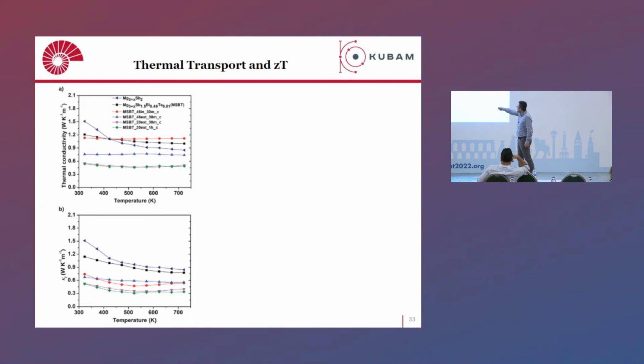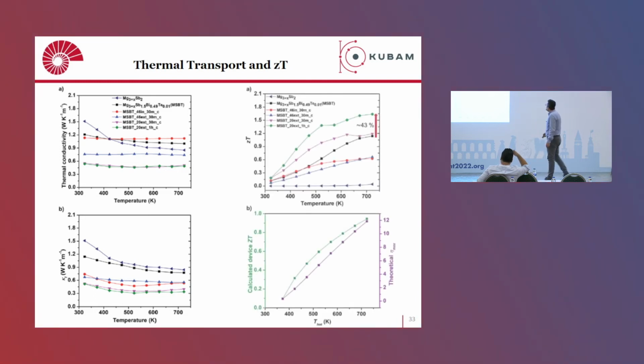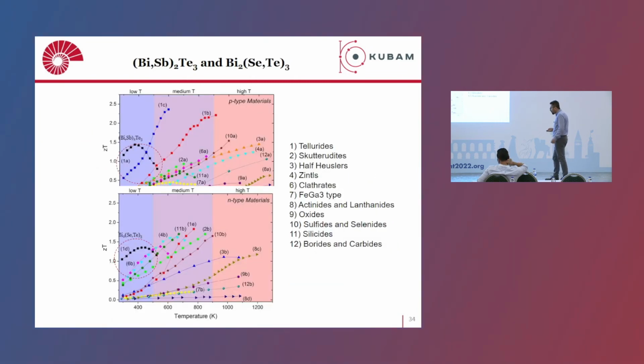This is undoped, this is doped material, around 1.2. When we do melt centrifugation, the total thermal conductivity is reduced by 50%. And lattice thermal conductivity as well. So this overall leads to around 43% enhancement if you just compare it with the MSBT phase. You can see it here. And if you calculate the device ZT, we can see that we can reach around 1 at this temperature, and the theoretical efficiency of this device would be around 12%. So these are not experimental, but theoretically calculated efficiencies. Okay, so far it was for magnesium antimonide.